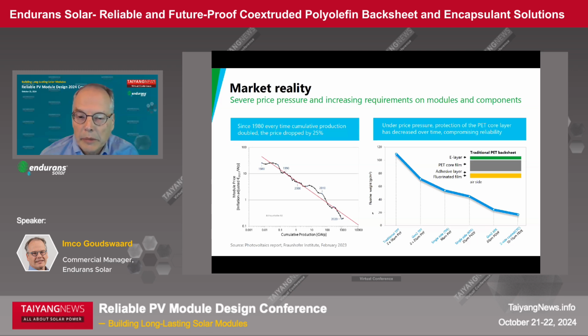But what happened in the past two decades is that where we started from a backsheet with a Tedlar fluoropolymer film on both sides, we gradually, forced by cost reductions, reduced the thickness of the Tedlar layer. Then we replaced one of the Tedlar layers by a cheaper fluoropolymer, PVDF. Also reduced that thickness again, and at the end we ended up with fluoropolymer which is just coated, like a 10 or 50 micron layer on top of the polyester. So that really shows you that due to the cost, the backsheet industry has compromised on quality, because this fluoropolymer is there to protect the polyester core layer.